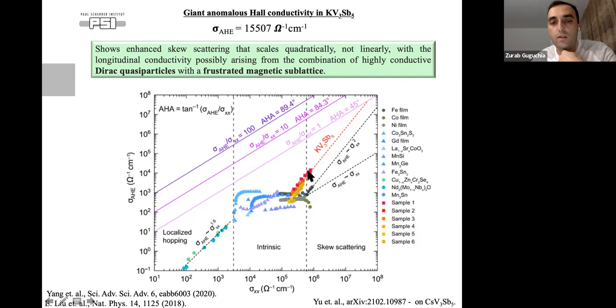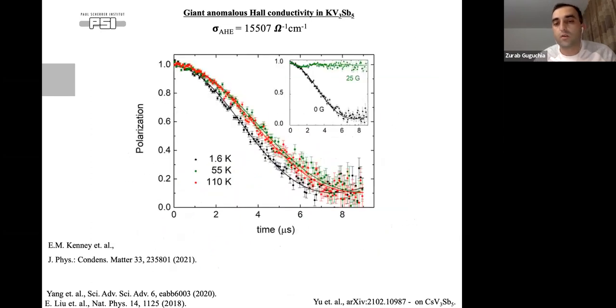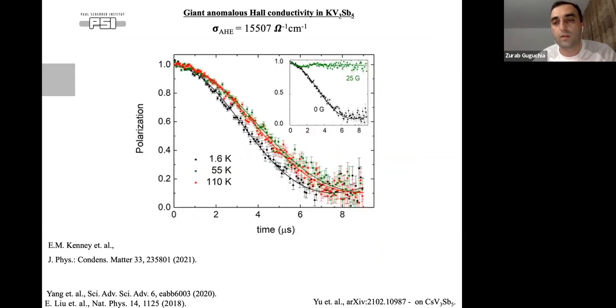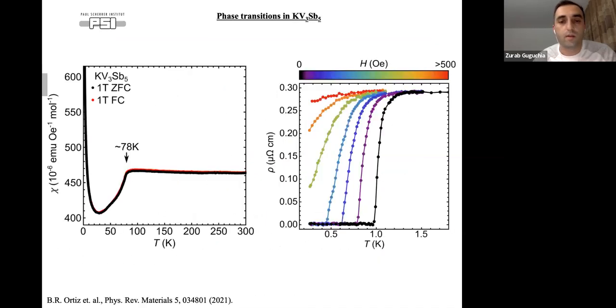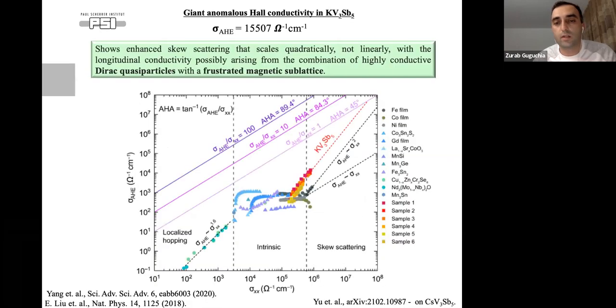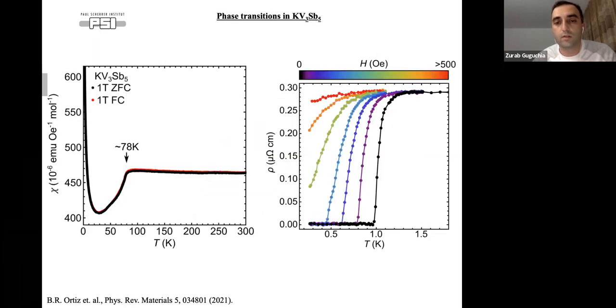While for the other compound, you find this quadratic scaling between anomalous Hall conductivity and longitudinal conductivity. And this was interpreted as skew scattering from the disordered spin clusters of the vanadium lattice. But then later on, from muSR experiments, it was shown that there is no long range or even short range magnetic ordering. And also neutron diffraction showed that there is no long range ordering in this material. So the interpretation of these clusters probably was not precise, but the experimental result was remarkable, showing the large anomalous Hall conductivity.